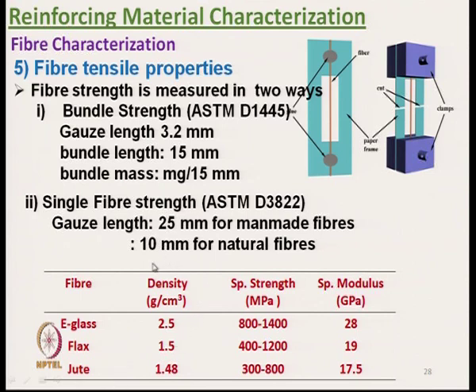Okay. And these are the typical characteristics of fiber strength, for fibers like e-glass, flax and jute. The density of e-glass is 2.5 gram per cc, 1.5 for flax, 1.48 for jute, and the strength typically for e-glass is 800 to 1400 megapascal, for flax around 400 to 1200 megapascal, and jute 300 to 800 megapascal, and specific modulus for glass is much higher than the flax and jute fibers.